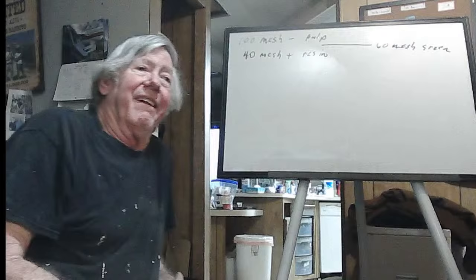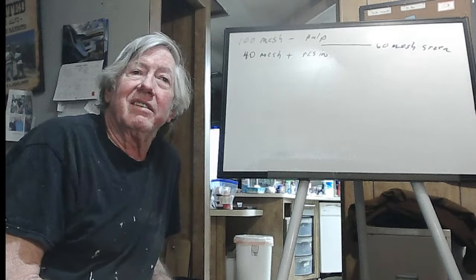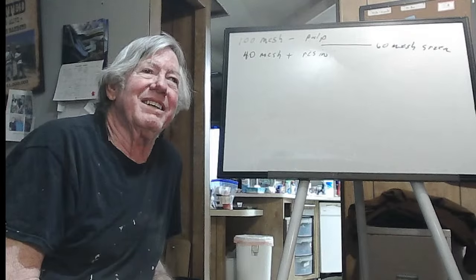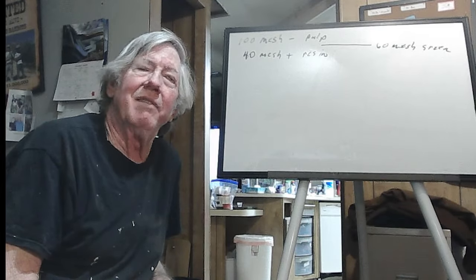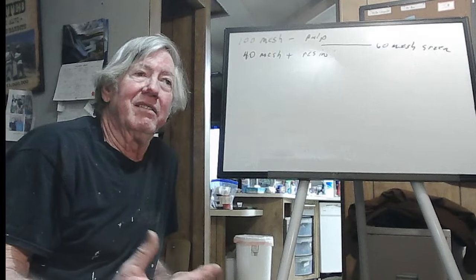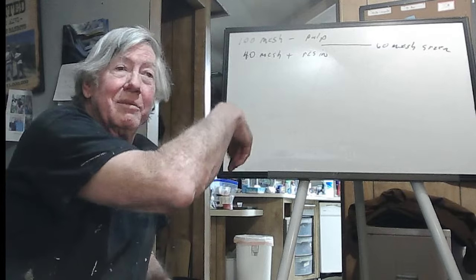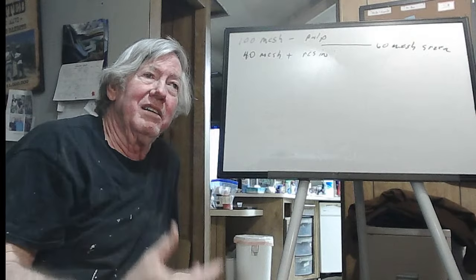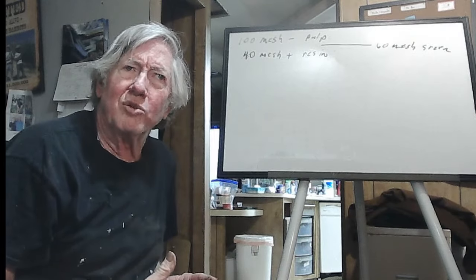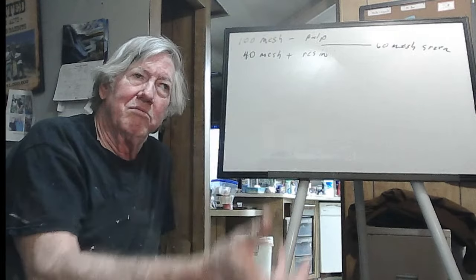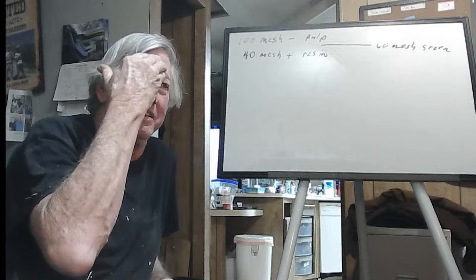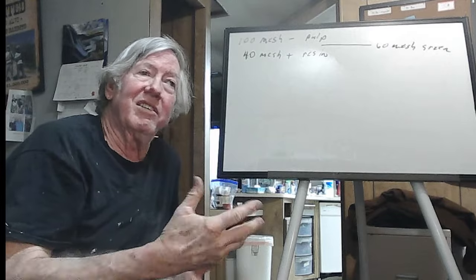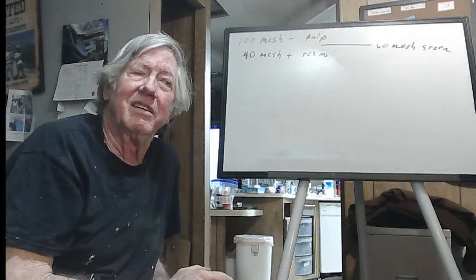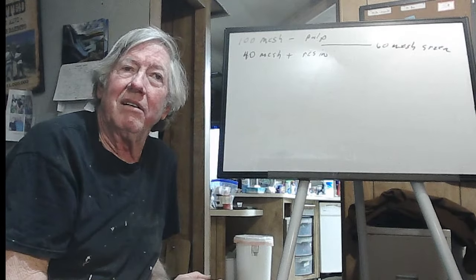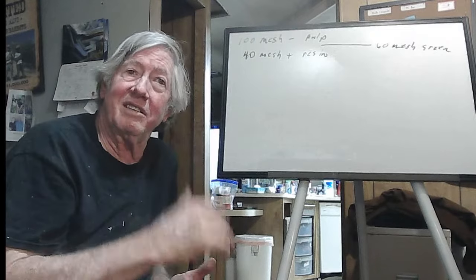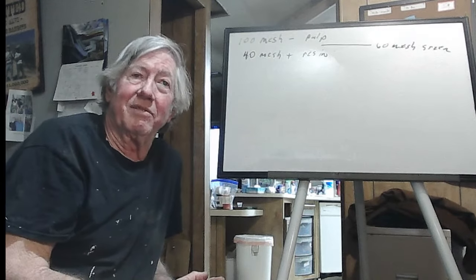So that's the concept of why resin in pulp is basically, theoretically, a very simple method. Now, I got to figure out all the chemistry and stuff. But you also have to have a screen when you have your pulp originally generated as it comes off the table. You need to make sure you don't have any significant amount of oversize, which may not be a problem at all. Don't know. That's what you test. If you don't have a problem, you don't need to screen it first.